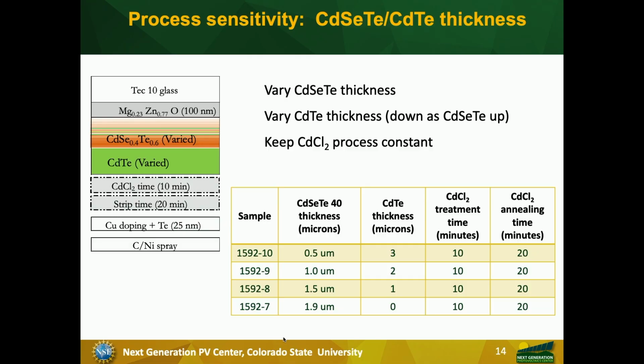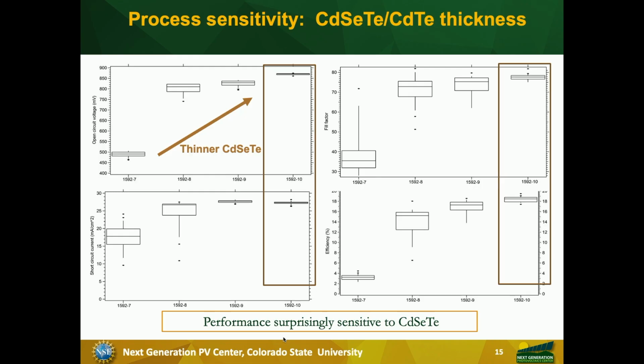And here is an example of varying the thickness of the first layer and looking at what happens to the process. And here you can see that there's a dramatic effect if you change the cadmium selenium telluride thickness. If it's all cadmium selenium telluride, it's 3% efficiency. And as you add more and more cadmium telluride at the back, the efficiency climbs. And here is a 19% device, 19% consistent production. When I show this chart, it's an average of about 25 different cells that have been made on this condition, and they are being compared.